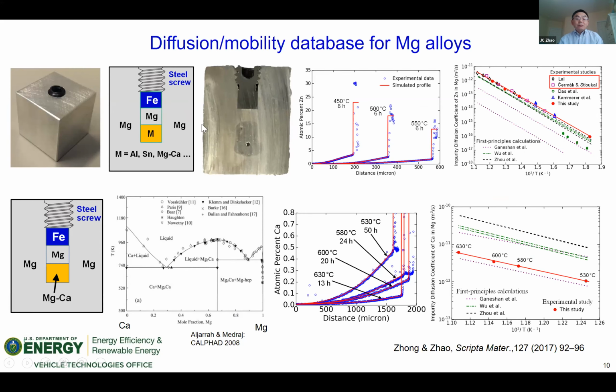This is all made inside a glove box, a pure argon glove box. And then we can take it out because there's so much contact here that when we take it out and seal it off in a quartz tube, during that process the oxygen cannot get in. And then we heat it up, melt it, and they form a eutectic, a pure liquid diffusing against the solid solution.